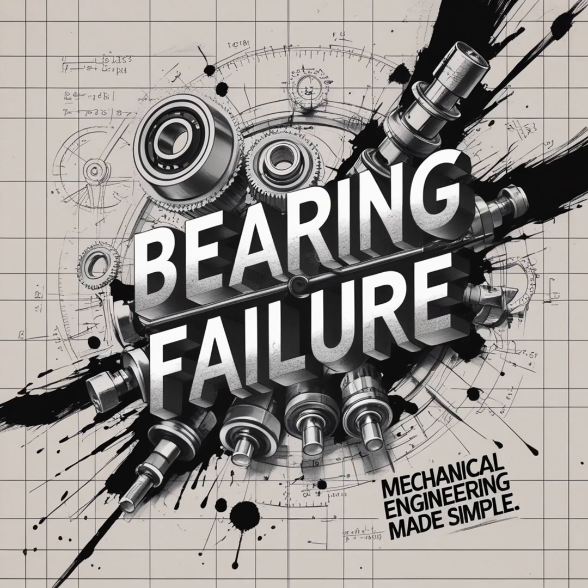And beyond just the geometry, what of the actual mounting technique itself? Oh, faulty mounting practices are catastrophic. This could be physical damage during transport or storage, or the classic mistake, forcing a fit with the wrong tools. The old hammer trick. The old hammer trick, exactly. Hitting an outer ring when it's mounted in a housing, or vice versa. These actions can induce instantaneous internal cracks or massive false Brinelling, causing immediate failure right on startup.